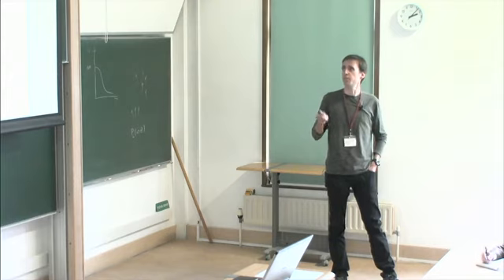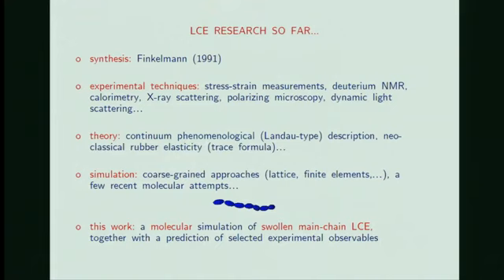This was implemented by the so-called two-step cross-linking procedure, where you first have weakly cross-linked polymer networks, then align your sample either by stretching or in an external field, and then perform a second cross-linking step, and this will imprint some easy axis into your system.